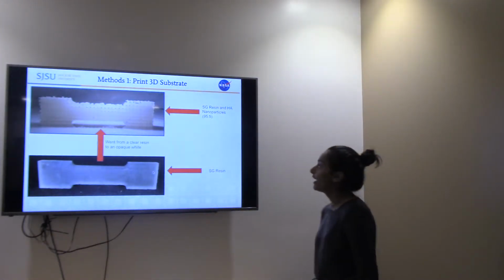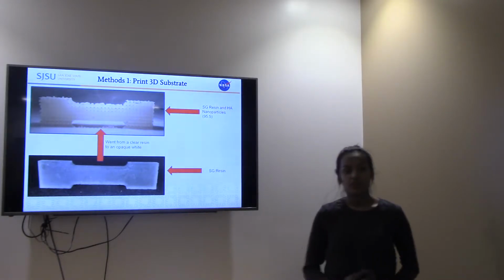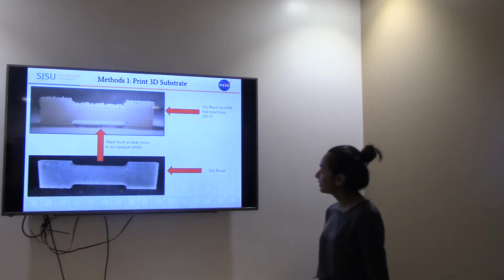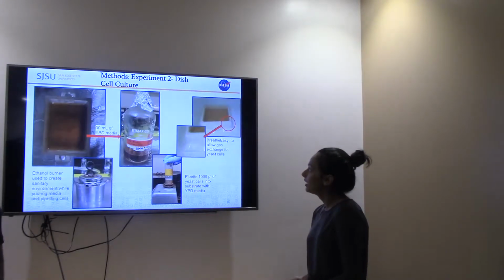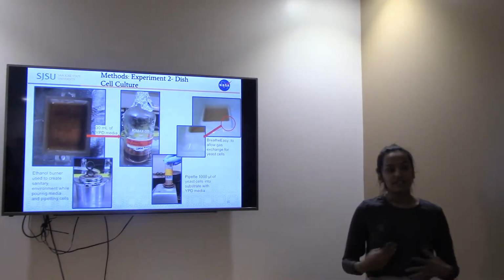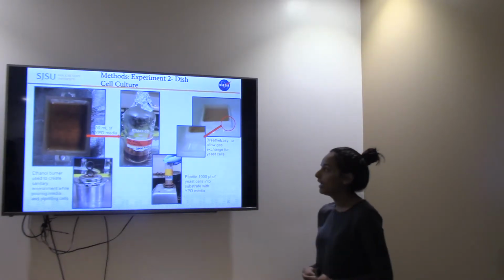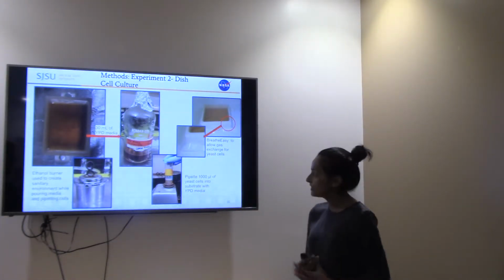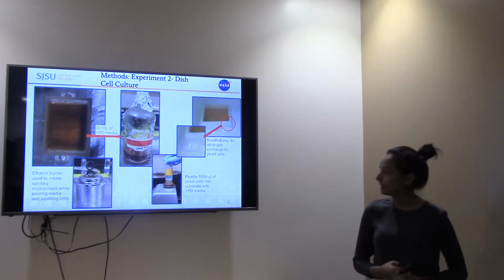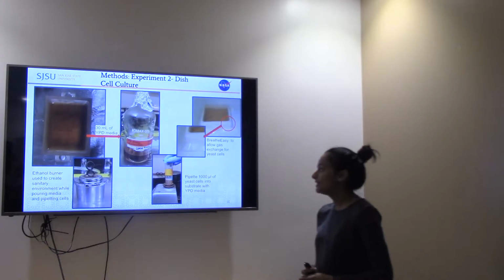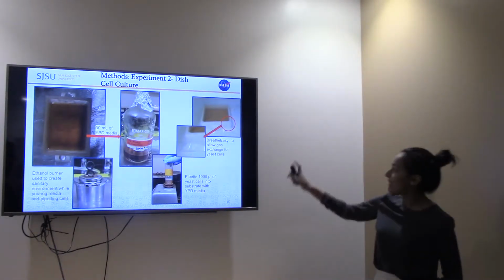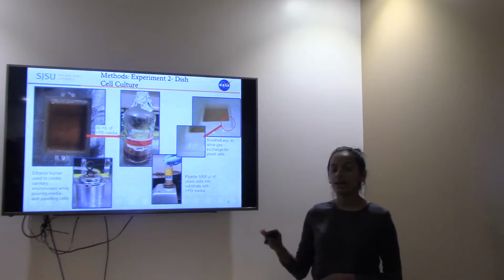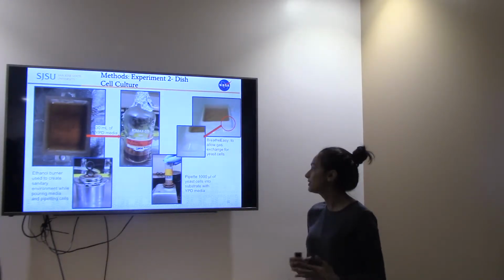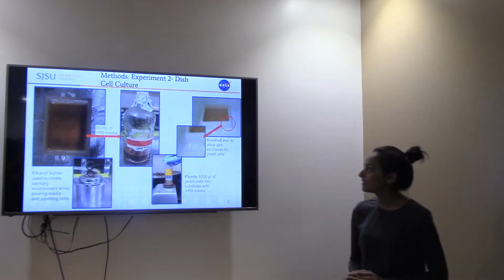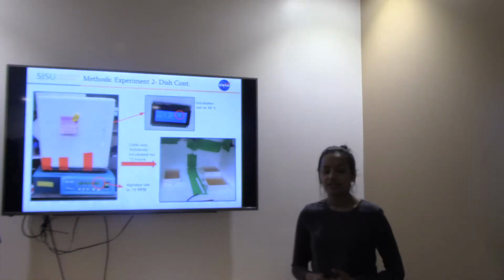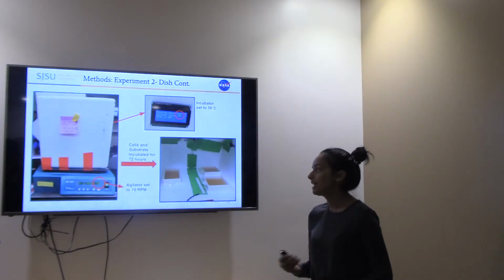What we observed was, with the addition of the Ag nanoparticles, the resin, which was initially clear, went to a more opaque white color, as you can see up there with the 5% ratio. For our first experiment, we were testing for biological responses, so we made a dish geometry with the SG resin, and we poured in 30 milliliters of YPD media and 1,000 microliters of yeast culture. After setting that up, we covered it loosely on top to prevent any spillage and to allow the cells gas exchange.